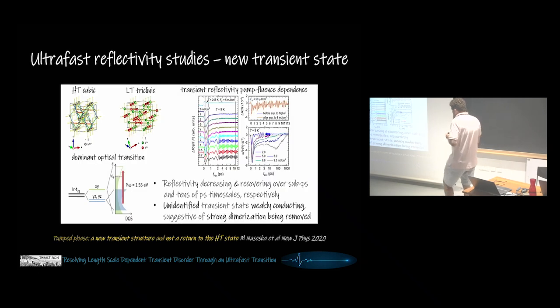Relatively recently, this system was looked at by the group in Ljubljana, and they studied ultrafast reflectivity. They claimed that there is a new transient state, where the reflectivity decreases initially and then recovers over sub-picosecond and tens-of-picosecond time scales respectively. This unidentified transient state appears to be weakly conducting. This was done at low temperature, which is suggestive of this strong dimerization being removed. And so we wanted to test what is happening with this system in the ultrafast regime from the local structural perspective.